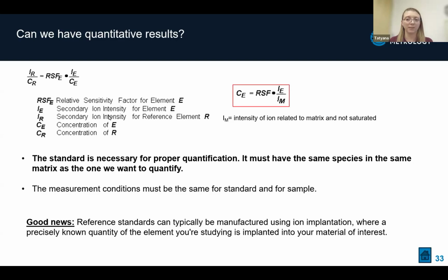Because of the very significant influence of the matrix on the ionization properties of the element of interest, to get reliable quantitative data, a specific standard is necessary. It must have the same species in the same matrix as the one we want to quantify. Also, the measurement conditions must be the same for standard and for sample. The good news is that this reference standard can be produced using ion implantation, allowing us to create almost any combination of element and matrices.